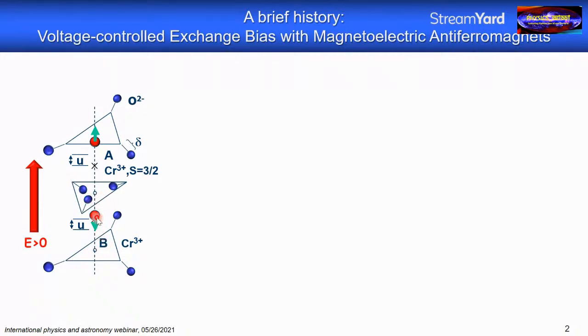But you notice this B atom here moves in towards the smaller triangle. This A atom moves towards this bigger triangle. And that has a profound effect because it lifts the degeneracy between the sublattice magnetization. So the antiferromagnet, which is down, up, down, up, down, up, is no longer fully compensated, but develops a small ferrimagnetic moment, M, and that moment in the linear magnetoelectric regime is proportional to the electric field, which is mediated here by this magnetoelectric susceptibility tensor.